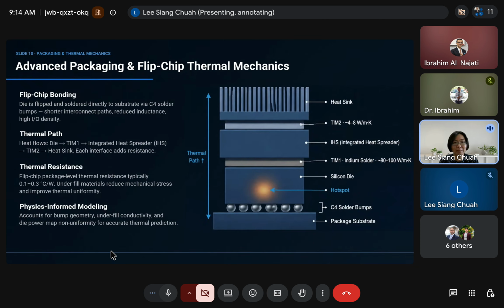With the thermal landscape in mind, we now look at how the heat actually moves through the modern chip package. The dominant architecture is flip-chip bonding, where the die is flipped and connected to the substrate through C4 solder bumps. This improves the electrical performance, but it also defines the thermal path. So the heat flows step by step. First from the die, to TIM1, the integrated heat spreader, TIM2, the heat sink, and finally the cooling system. So each interface adds thermal resistance. At the package level, the total thermal resistance is typically 0.1 to 0.3, meaning even small improvements significantly reduce the junction temperature.